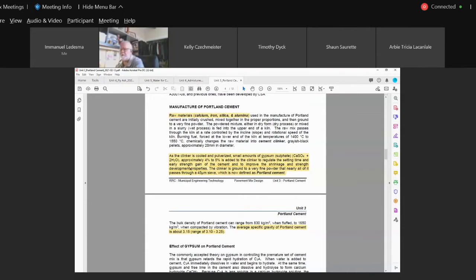Now, one more thing we have to do here. As the clinker is cooled and pulverized -- you're grinding it -- small amounts of gypsum, 4 to 5%, is added to the clinker. The reason for that is you want to regulate the setting time of the cement, develop early strength gain, and improve its shrinkage.